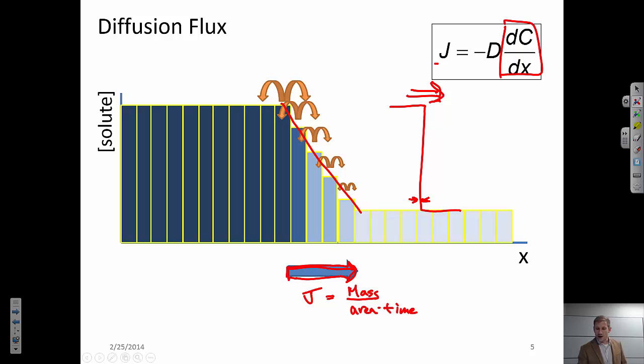Now there's one thing that we haven't talked about yet and that's this constant. So I keep saying that the flux is proportional to this compositional gradient. And what is controlling that proportionality? Well, that's a function of a number of things. It's a function of how easily does this solute species move around. Is it a small atom that can move fast? Is it a larger atom? What is the diffusion mechanism? Is it interstitial or is it substitutional? What is the crystal structure that we're diffusing through? So a lot of things come into play that affect this diffusion constant, and that's what we call it.